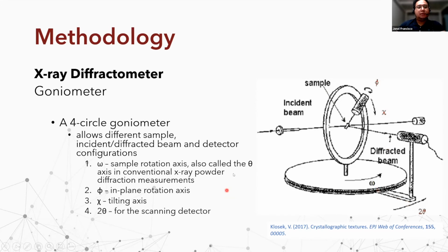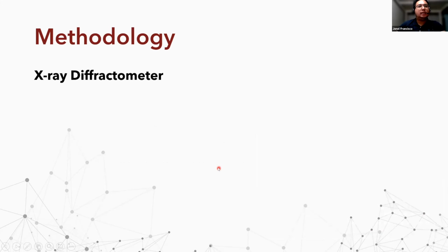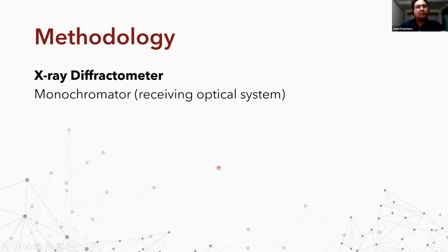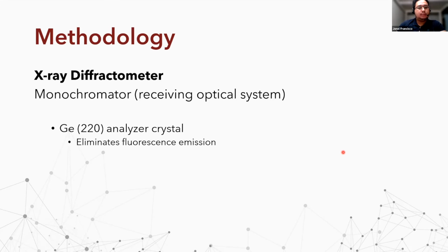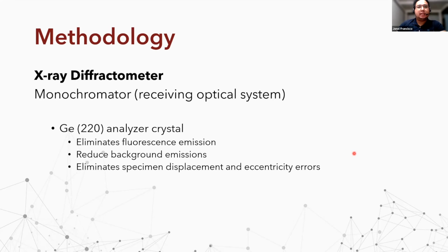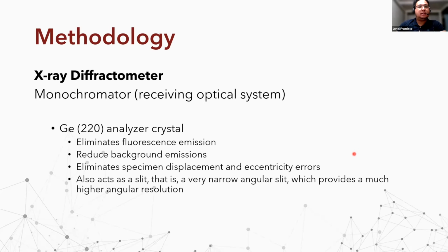After passing through the sample, the diffracted beam is further enhanced by another monochromator, this time from the receiving optical system, before it reaches the detector. In this study, a germanium 220 analyzer crystal was employed. Similar to the incident beam monochromator, it was employed to increase the resolution of the diffracted beam. It also eliminates fluorescence emission, reduces background emission, and eliminates specimen displacement and eccentricity error. It can also act as a very narrow angular slit, which provides a much higher angular resolution.